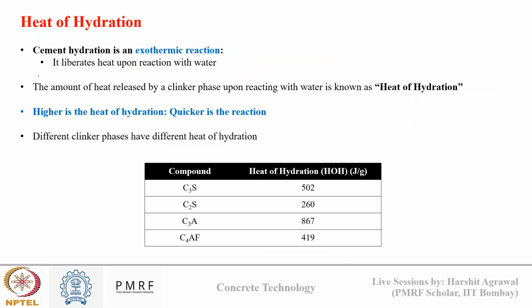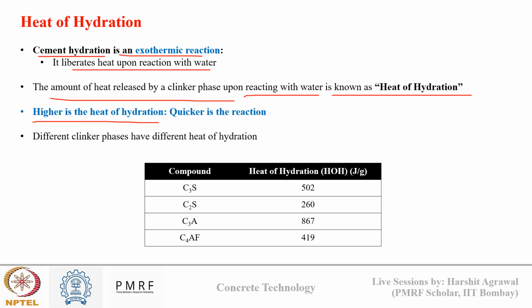After degree of hydration, we have heat of hydration. So when we talk about cement hydration, we should remember that cement hydration is an exothermic reaction. It liberates heat when water is added to cement. As hydration occurs, heat is liberated from the system. So the amount of heat released by a clinker phase upon reacting with water is known as heat of hydration. Okay. Now, since heat is released during hydration, we can say higher is the heat of hydration, quicker is the reaction. Okay, so as more cement reacts, more heat will be produced. So higher is the heat of reaction, quicker is the reaction because more cement is reacting. And that's why finer cement has more surface area, so it can react with more water, so it will have higher heat of hydration also. More exothermic reaction will also occur in fine grains.